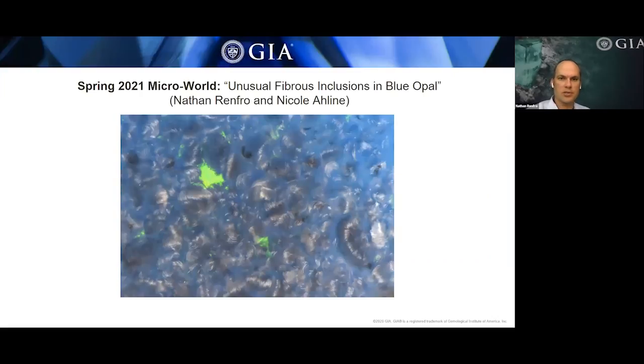Also observed in an interesting opal were these coiled fibrous inclusions. Most likely this opal was from the Sinaloa area of Mexico, where you do have this sort of natural blue body color opal. The body color is typically sort of a grayish blue, but these little coils of fibrous inclusions were the first that I'd seen in a stone like this. Unfortunately, we weren't able to identify what they were using Raman spectroscopy, so they may have been altered by the opalization process, but they were still quite interesting to observe.